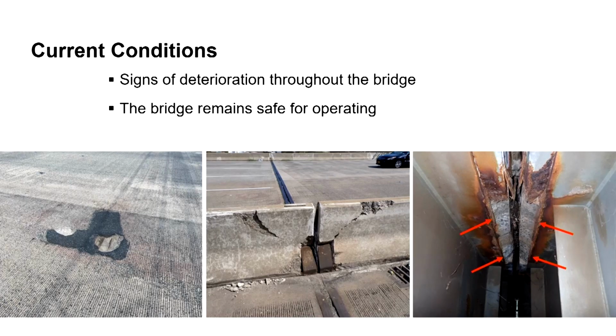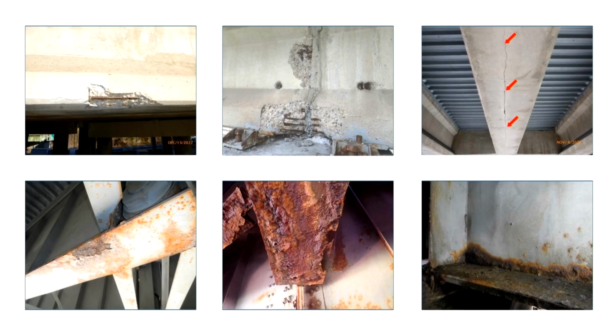Here we wanted to show most of the types of deterioration throughout the project. As you can see, there are parapets that have damaged delamination or cracks on them. Typical deck crack and delamination throughout the project, and joint failure. Almost every joint on that bridge, actually every joint on that bridge, has failed. There is still beam corrosion throughout the project. Pre-stressed concrete beams have cracked due to post-tensioning duct corrosion.